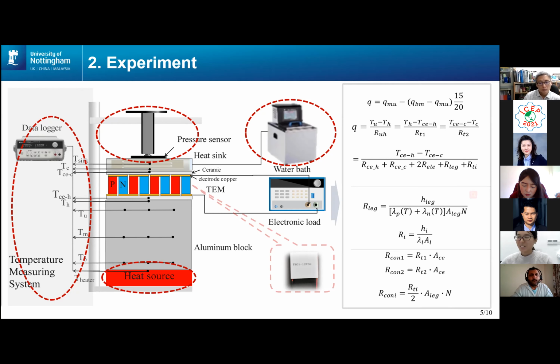Yes, we do see some mechanical damage on the TEG module because the ceramic layer in the TEG module is quite fragile. If the pressure is very large, it may be broken. So that is a difficult question. But there's no damage to the electrical contacts? The electrical contact is inside the P and N junctions. Yes, if the TEG module is broken, the thermal contact resistance will increase largely.